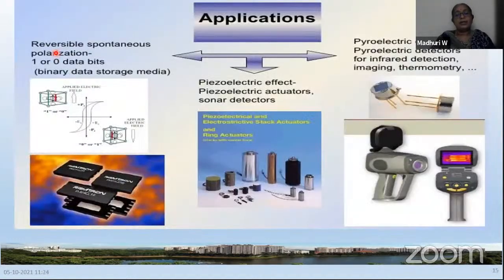And these are a few applications of piezoelectrics, wherein you can see here, this is a read-write data. As I told you, we have a hysteresis loop, or there is a hysteresis behavior between the electric field and the polarization. And you can see that this is a very soft loop with very little coercivity. Usually we go with the AC field. In your AC field, your field goes up, takes a maxima, comes down to zero, and then goes to the negative part. You know what an AC electric field is?